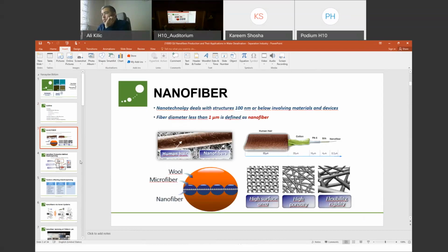They are generally defined as fibers with a diameter of less than 1 micrometer. You can compare here with human hair. We can reduce the fiber diameters down to 50 nanometers. Actually, here I mentioned 0.2 micrometer, but we can reduce it to 50 nanometers. This brings us very high surface area and very high porosity, which also makes these materials very